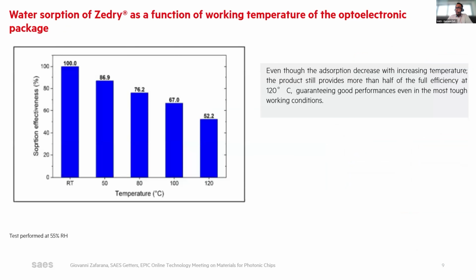In our laboratory, we perform tests to understand the absorption performance, in particular changing the temperature of the devices. We showed that increasing the temperature from room temperature to 120 Celsius, the absorption still remained at 50% of the effective absorption. So the question is, what is the remaining water inside the package? For that, we are measuring the water isotherm in order to understand, as the temperature increases, what humidity still remains inside the packages.